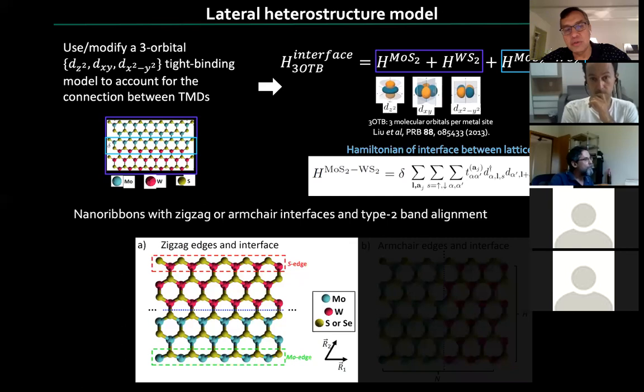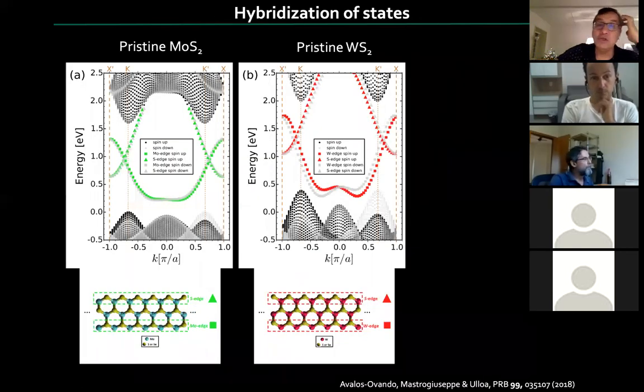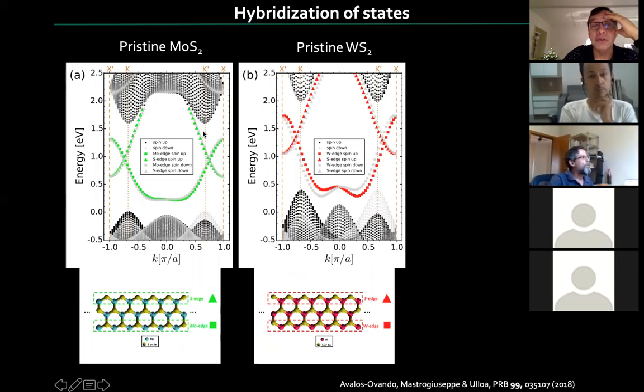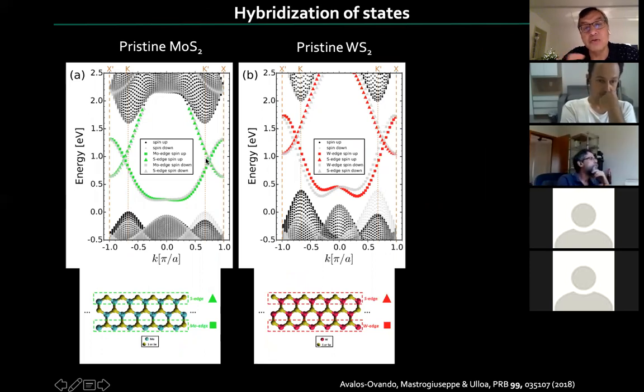Before I show you the results for this interface, let me show you the results for the separate ribbons. Here on the left, in green colors, you see these edge states that I argued for before. This is the K point; you see those have the edge states. This is the other K point. You can barely see them in this slide, but there are gray and green triangles corresponding to the two helicities, the two different spin species. So there are four levels there.